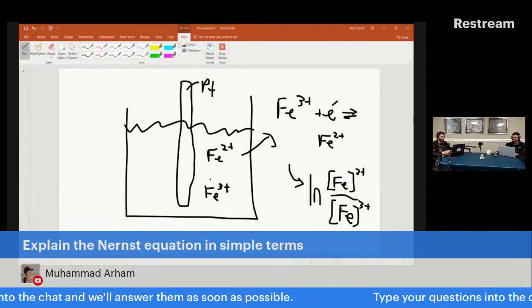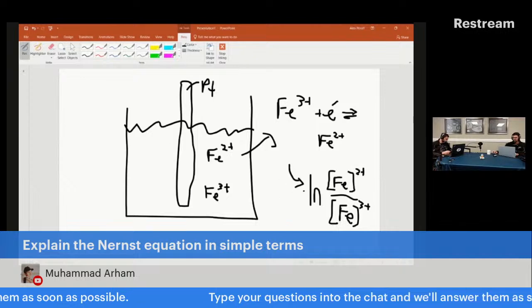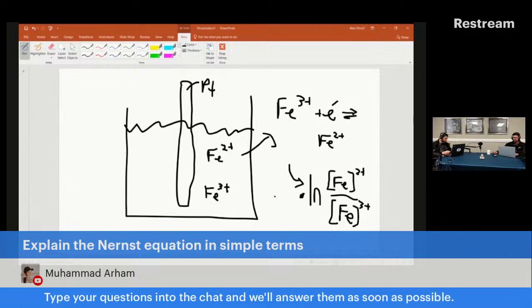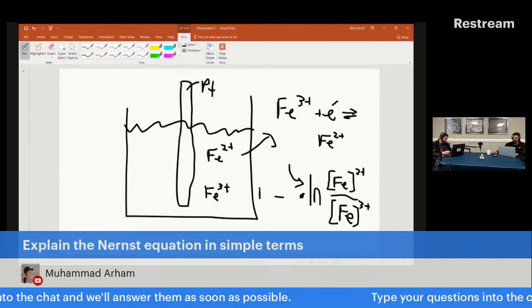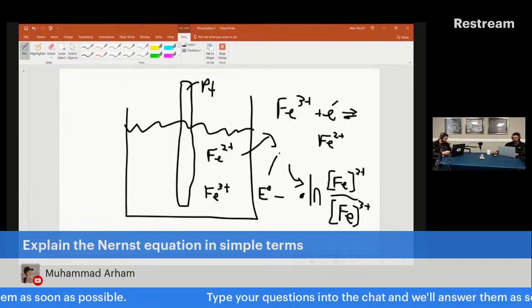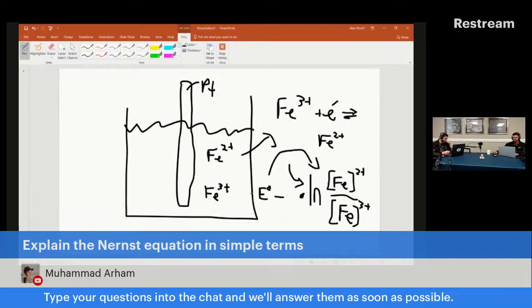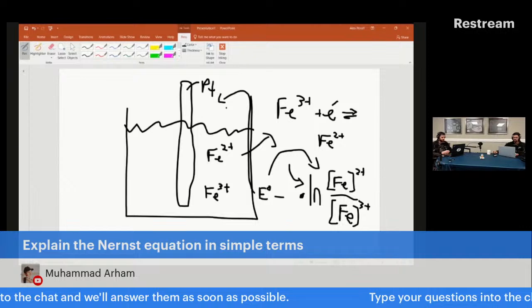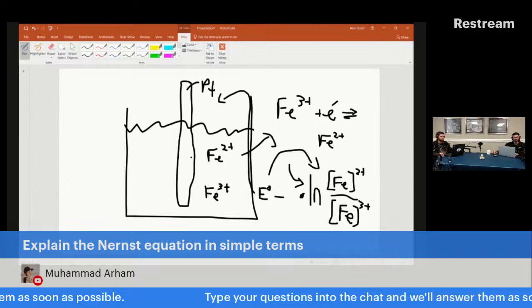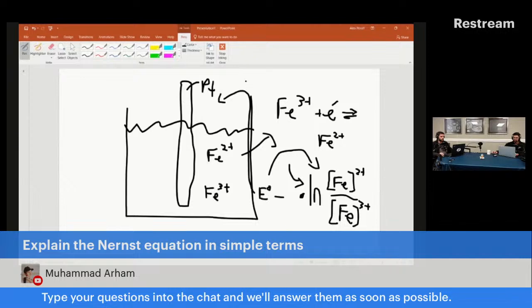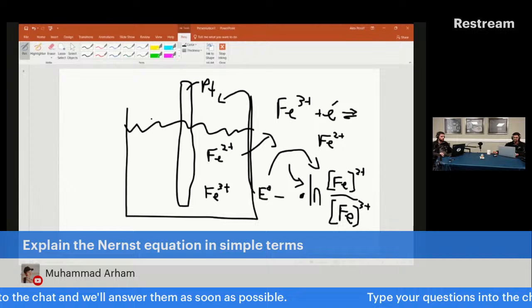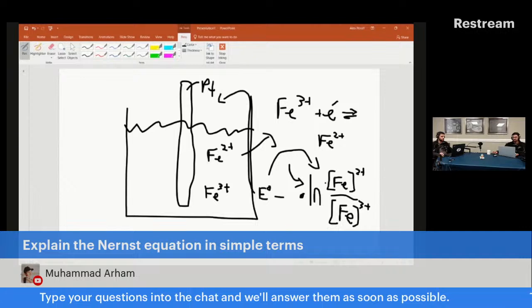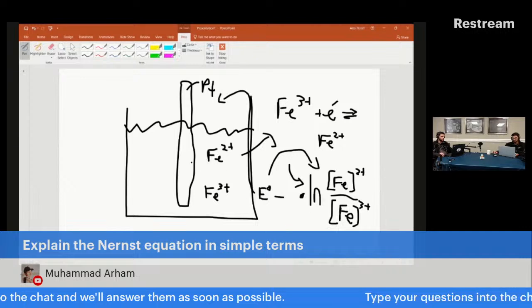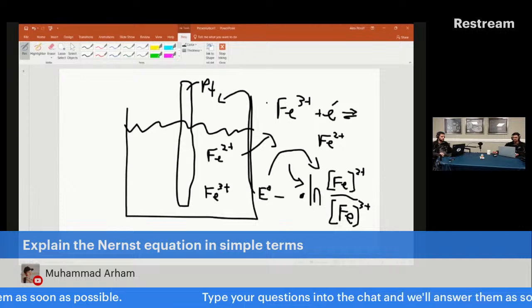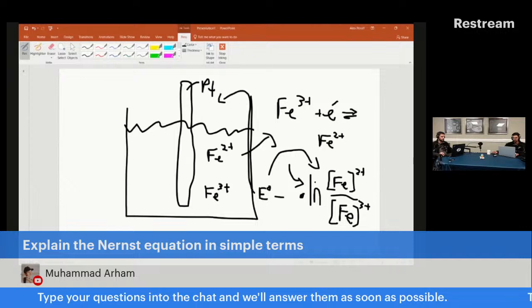But the key is that this times some constants, Faraday's constant and all that stuff, minus the standard redox potential of this reaction will get you the potential of your, or in this case, the Fermi level of this platinum wire. So this will give you the Fermi level, or just the potential if we had another electrode here. So the surface potential or the Fermi level of this platinum will be governed by the relative concentration of redox species in solution. And so that is one way of thinking conceptually about how the Nernst equation works.